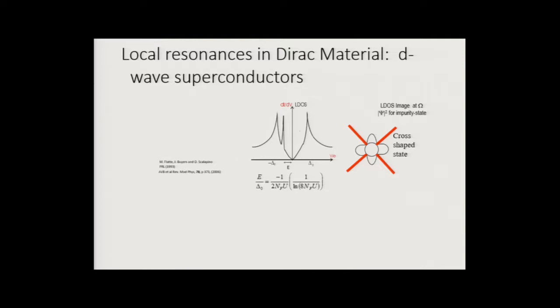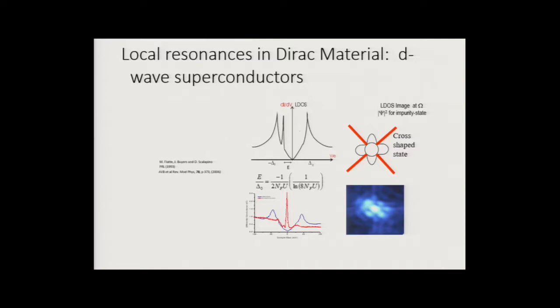The energy of this resonance for this particular calculation tends to zero as the strength of the impurity grows. So the harder the impurity is, the stronger the impurity scattering is, the softer the resonance is. This is a very, very non-metallic response. So that's another example of the Dirac physics, actually: you do this very strong impurity, and you're producing a very low-lying resonance. Okay, this is another example of universality.